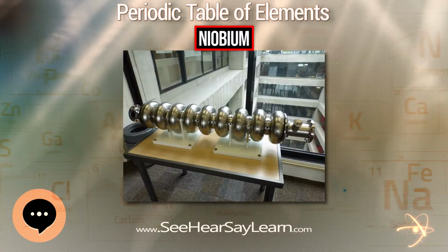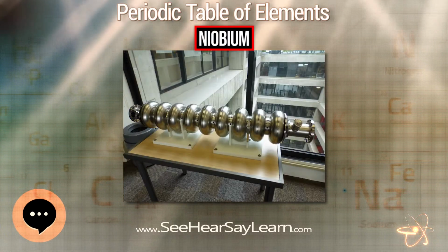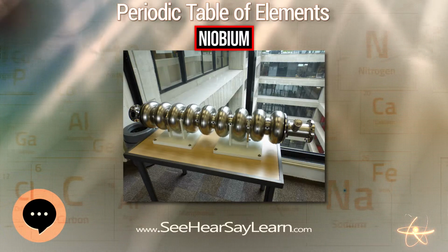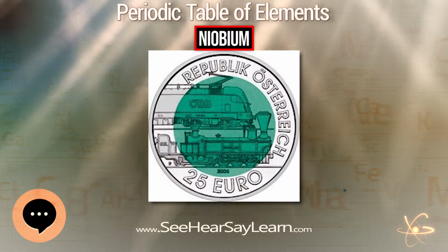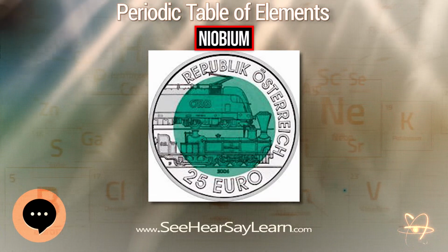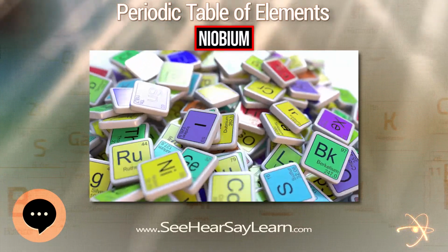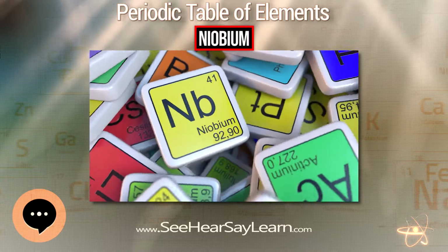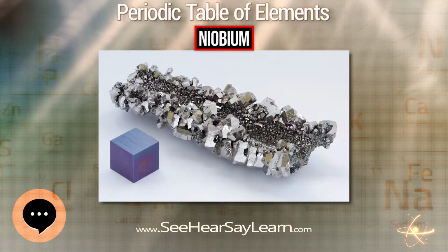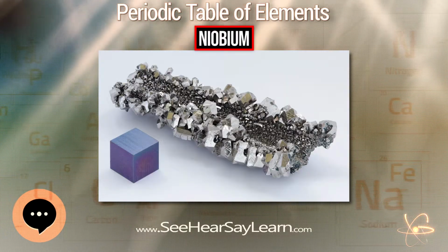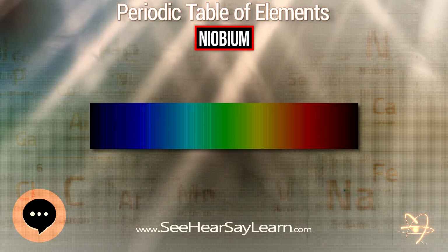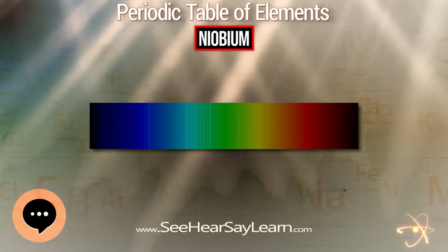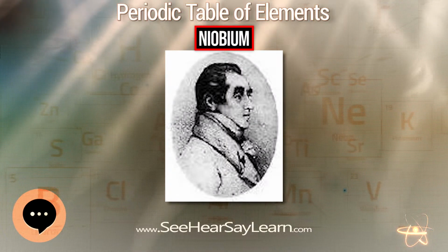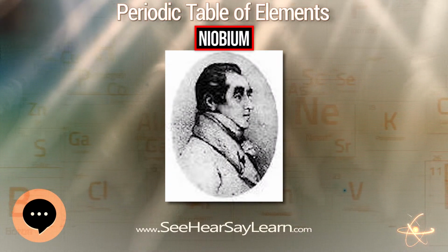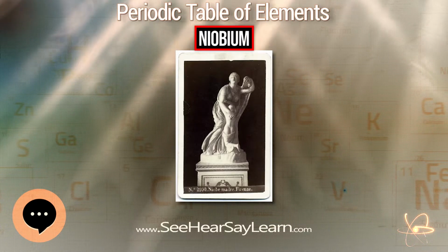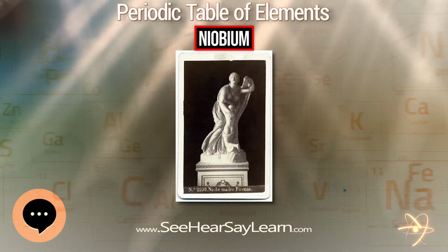Niobium precipitates a hardening gamma double prime phase within the grain structure of the superalloy. One example superalloy is Inconel 718, consisting of roughly 50% nickel, 18.6% chromium, 18.5% iron, 5% niobium, 3.1% molybdenum, 0.9% titanium, and 0.4% aluminium. These superalloys were used, for example, in advanced airframe systems for the Gemini program. Another niobium alloy was used for the nozzle of the Apollo service module.